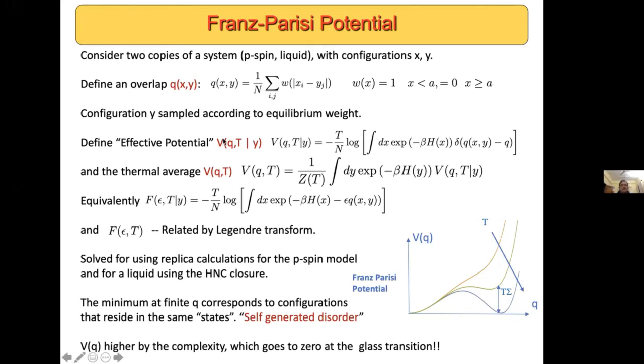Okay, so one of the initial and appealing ways of trying to do a replica theory is the so-called Franz-Parisi potential. And the basic idea is one considers two copies of a system, and this was done for spin models initially, but later for liquids, where one of the copies acts as an applied field on the other. So in other words, one considers one of those copies to be fixed in some configuration and evaluates an effective potential for the other copy as a function of the overlap between them. So this is like a Landau free energy with Q as the order parameter, with the configuration of the second, the master copy, fixed.